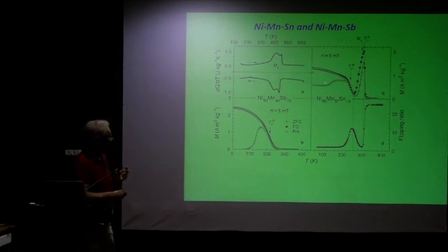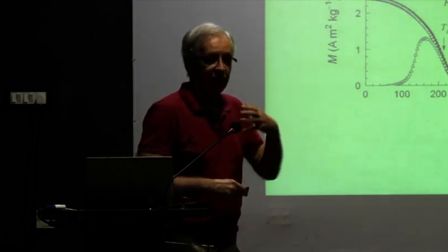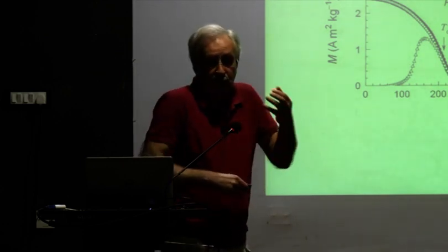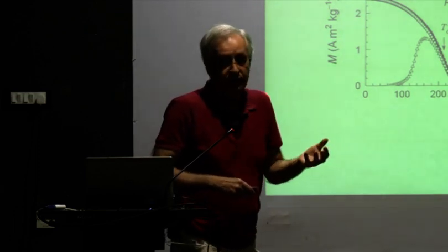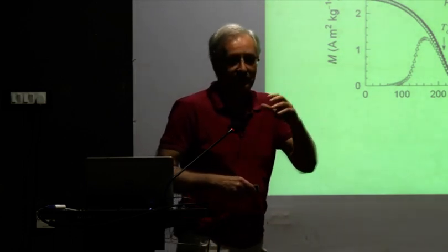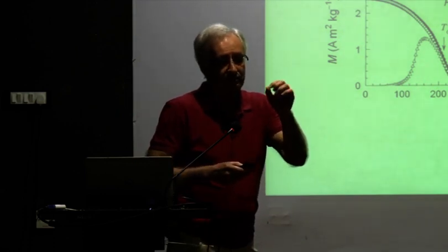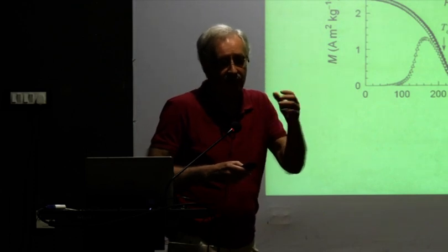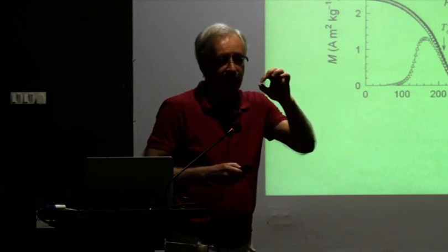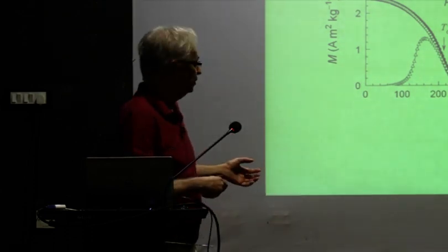So this region over here, what we call the superparamagnetic, is perhaps not fully superparamagnetic, but there are magnetic domains built in there. If you don't have domains, you don't have depolarization. And in a superparamagnet, you don't have domains. But it could be that, if the superparamagnetic parts are large enough and there is an abrupt change in the magnetization where the superparamagnetic parts are sitting in the antiferromagnetic matrix, then there could be a depolarization due to that. That we don't know exactly.